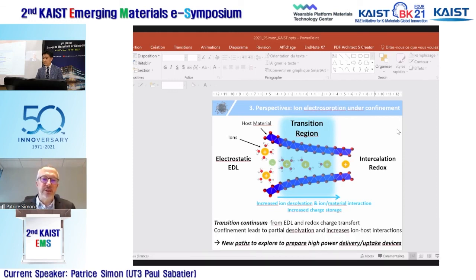Okay, thank you. Another question, I wonder if there is an impact of changing the capacitance property depending on the shape of the layer or the aspect ratio. I'm not sure that I get completely the point, but if the question is the aspect ratio, the size of a layer, if the question deals with interlayer distance, yeah, definitely, there will be a change in the capacitance property. But I think that this is more for 2D MXene. This is driven also by the surface chemistry. As I show, if you remove OH group, if you replace fluorine with chlorine, you really change the electrochemistry. And I think that the most critical change will be given by the surface chemistry.